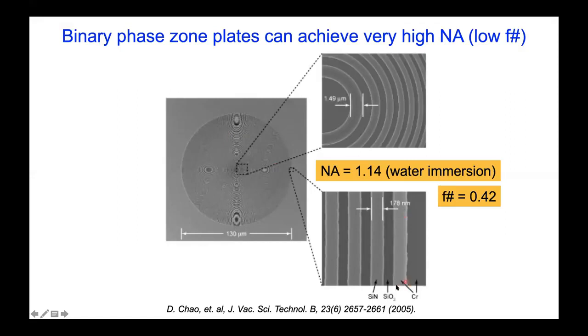So you can see the details here. It's a fused silica substrate with patterned silicon nitride. There's a chromium mask on the outside. So this arrow is actually wrong. It should be just on the outside to form the aperture. Now, the water fills in these gaps, and water and silicon nitride provide the index contrast to provide the appropriate phase shift. So this corresponded to a numerical aperture of 1.14 and an F number of 0.42.